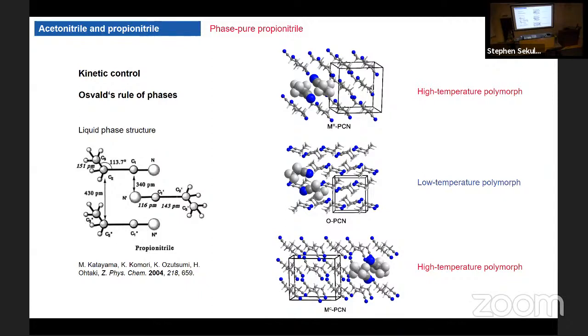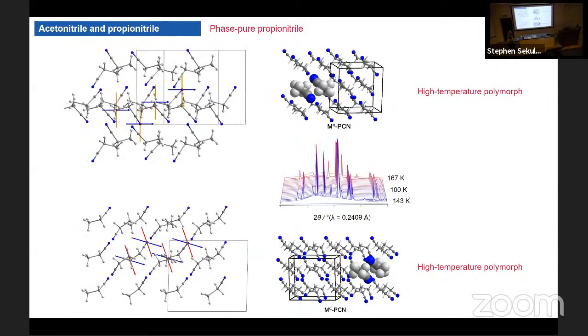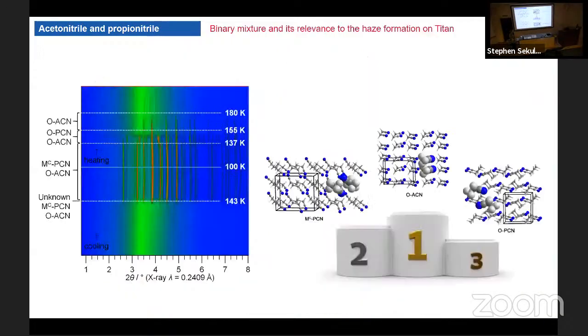But as you can see, a similar type of structure we have in the low temperature form as well. And that might be the reason why there is not that much quenching, meaning it is very easy to go from this polymorph to this one, as opposed to acetonitrile, in which flipping of whole layers should occur. This is how the patterns look. We also notice quite interesting structural effects in these two polymorphs, but we don't really have time to talk about it. But we will move to a mixture.